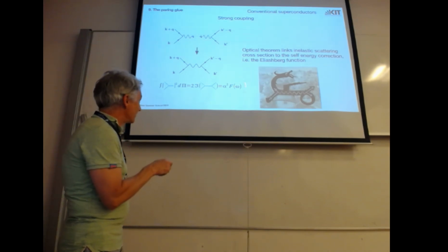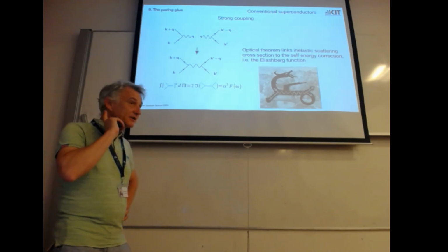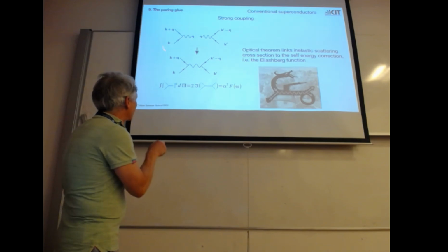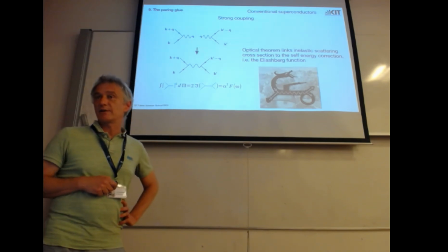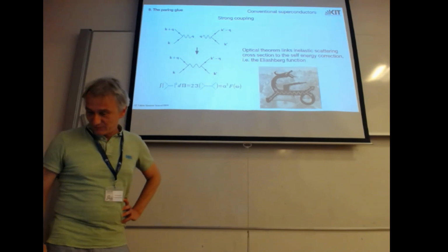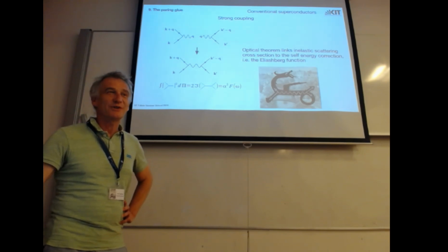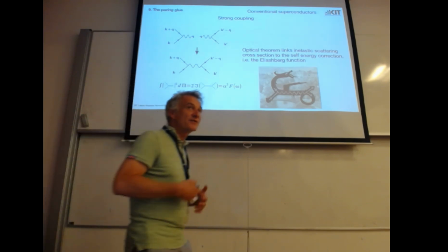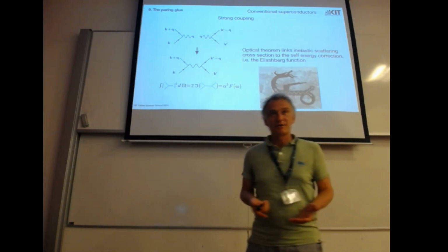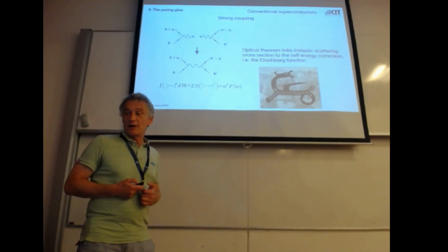So my statement now is we can measure this Eliashberg function when the superconductor is in the normal state, directly, when measuring the inelastic tunnel current. And that is actually a very nice statement, so you don't have to do very complicated data analysis before you use the McMillan inversion algorithm.